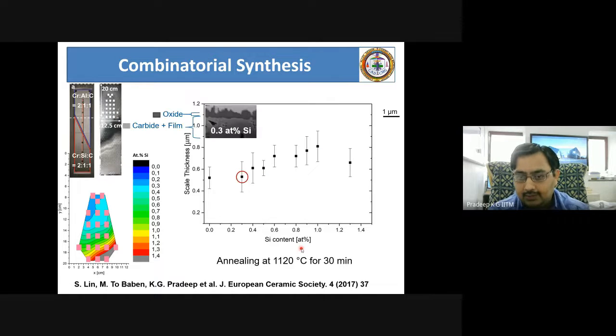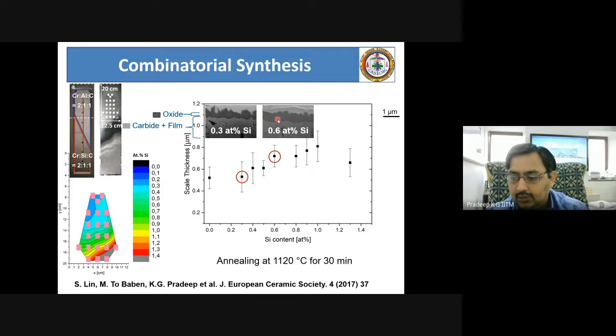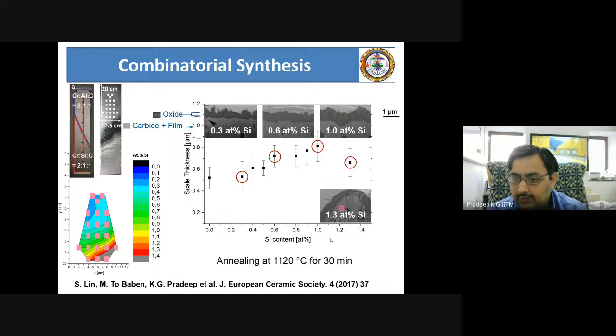As you notice here, this is the oxide that is formed with 0.3% silicon. With more increase in silicon content, the layer thickness increases, and at 1% silicon you have the highest thickness of the oxide scale, which is responsible for the self-healing behavior. When you increase silicon beyond 1%, the layer thickness decreases, and therefore you have a loss in layer thickness, or a reduction in self-healing.